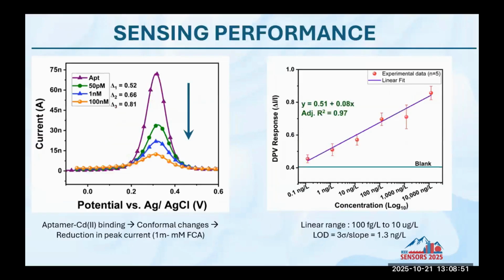Now, in order to do the sensing, we observed the peak current using the differential pulse voltammetry technique. What we observe is, after the aptamer step, when we incubate the sensor with a spiked concentration of DI water with cadmium ion, the current level decreases. As we increase the concentration, the current level further decreases. Why does this happen? This is because the aptamer undergoes a conformational change in its structure when it binds with heavy metal ions. This change in the structure restricts the electron flow at the interface, because of which the current level goes on decreasing.